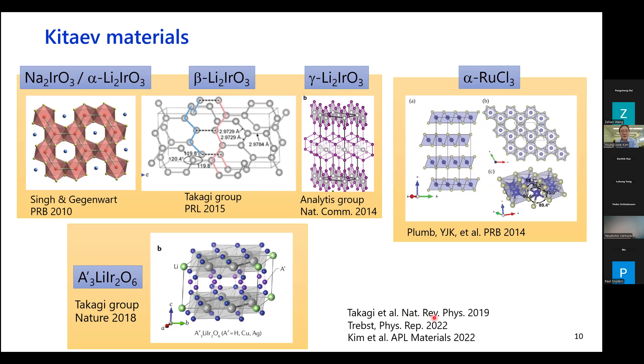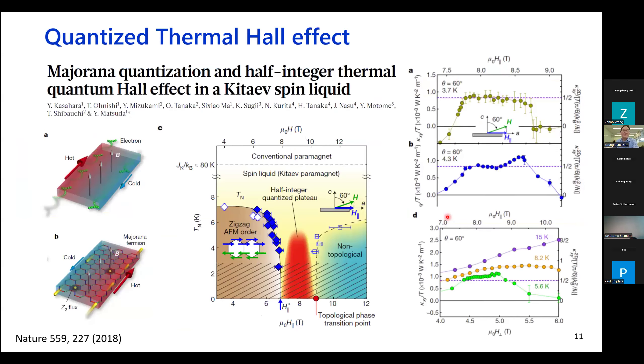This gave rise to many so-called Kitaev materials, a very popular topic over the last decade. Na₂IrO₃ and Li₂IrO₃ came along first, along with a 3D version of Li₂IrO₃ and an intercalated version discovered by Hidenori Takagi's group. Ruthenium chloride wasn't initially drawing much attention because ruthenium has weaker spin-orbit coupling, but we found that its idealized crystal structure actually allows us to think about Kitaev physics.